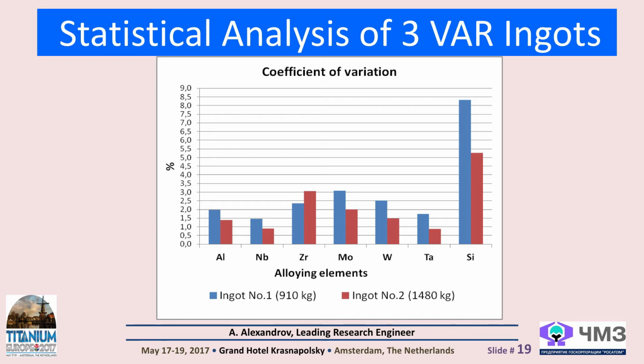High homogeneity of the ingot's chemical composition is confirmed by the accepted position that if the coefficient of variation is less than 10%, the variability is considered to be insignificant. And the comparison of ingots number 1 and number 2 in terms of the uniformity of the alloying elements distribution along their height indicates that in this particular case, ingot number 2 with the larger weight is more homogeneous. Only these concrete ingots, because it's not a rule.